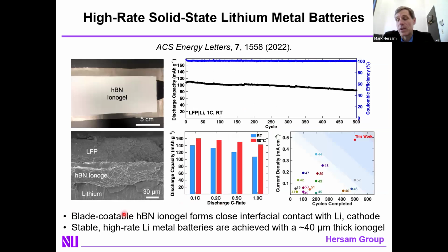This works quite nicely. You can go to large areas trivially. Because it goes down wet, you can conform your gel, even though its final state is very stiff. When it goes down, it's soft because it's still having large diluent solvent concentration. And so you can conform to irregular surfaces that are inevitable in batteries, and then drive gelation to get all the desirable mechanical and electrochemical properties.